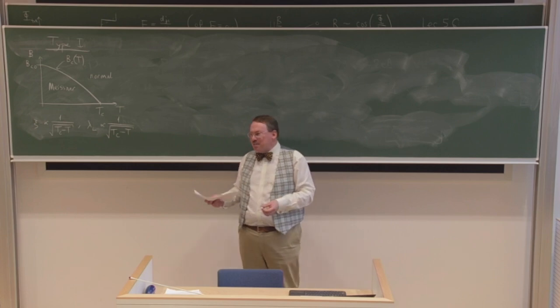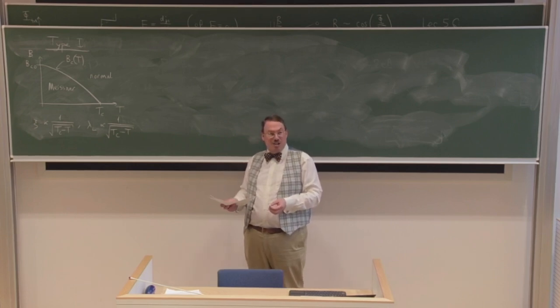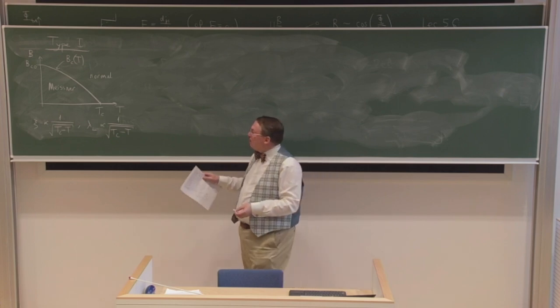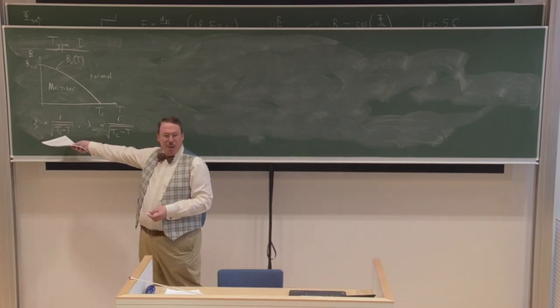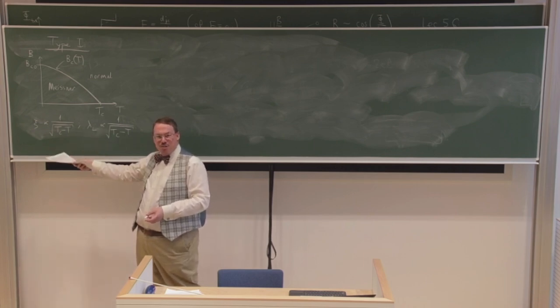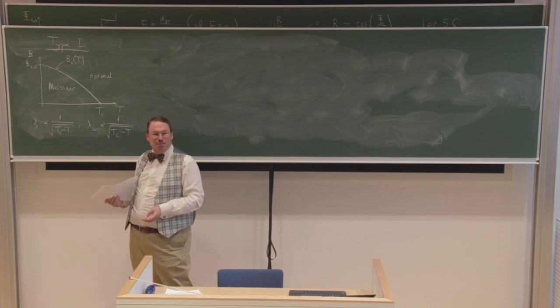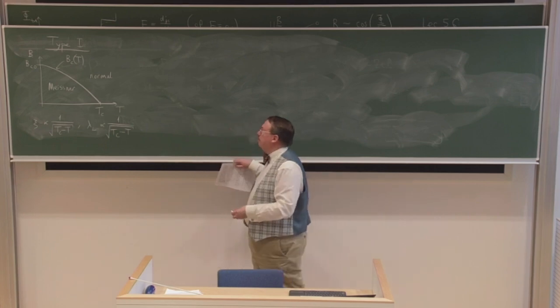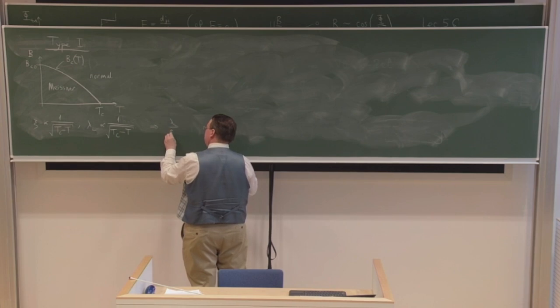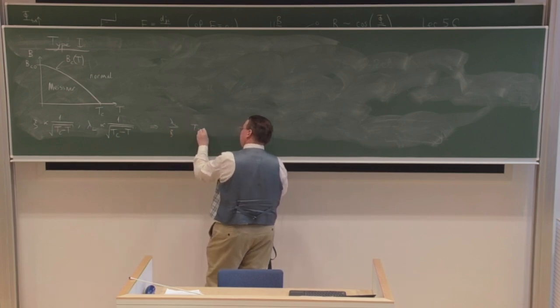It wouldn't have been crazy to think that maybe that calculation changed significantly as the temperature was raised. In Ginzburg-Landau theory, it doesn't. So the vortex cores get bigger as you heat the superconductor, but the field also penetrates better. And so if it was worth making a vortex at low temperatures, it's worth making one at high temperatures too. But again, this calls into question a lot of our fundamental assumptions with Ginzburg-Landau theory, right?